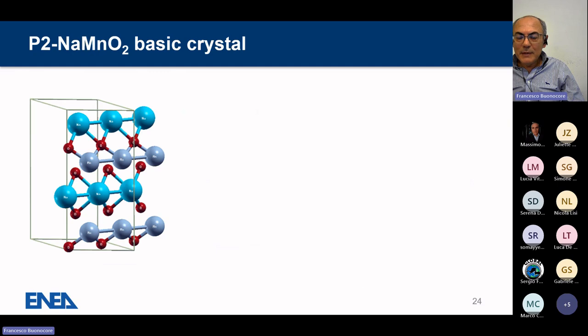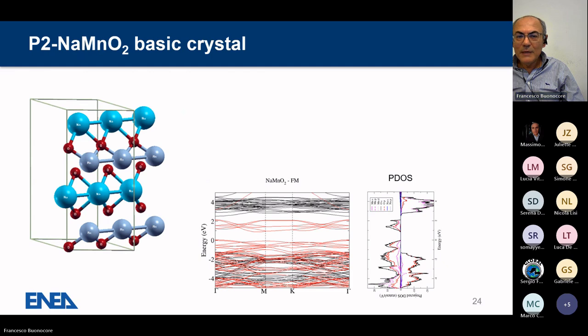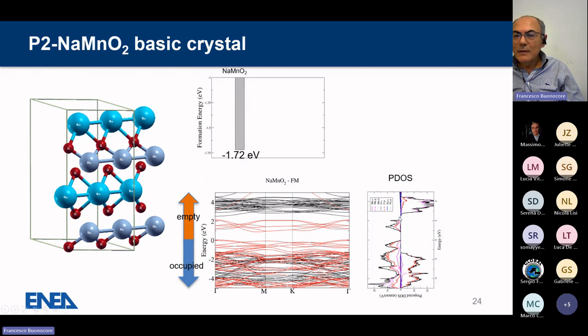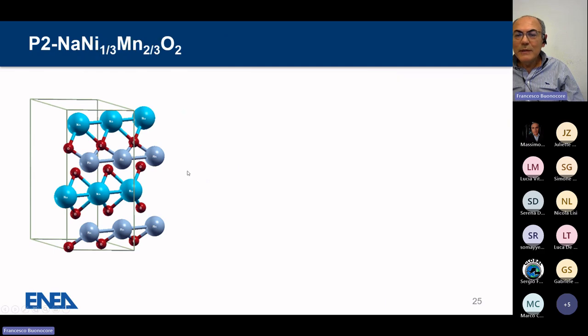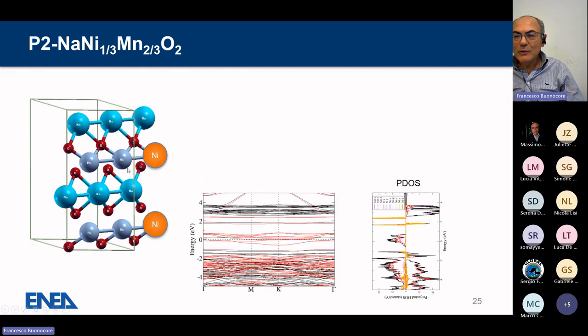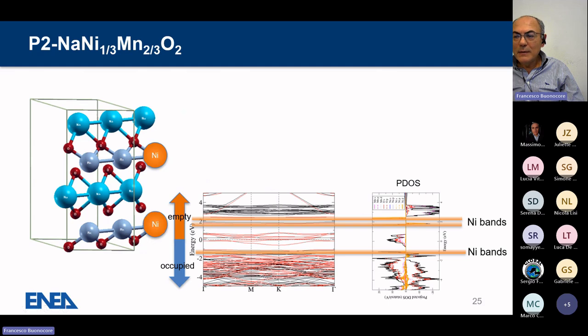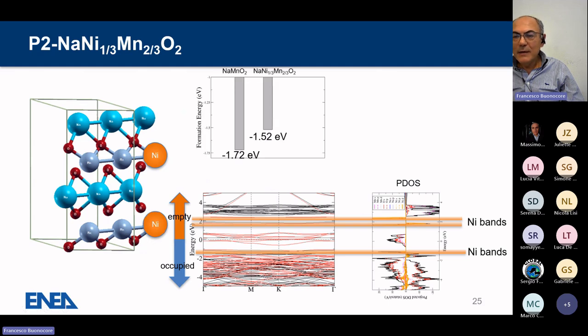And in the next presentation, Marco will tell us more about this. This is some example for some crystal we have selected. This is a crystal with 24 atoms. We calculated the band structure, the density of states, the formation energy and the redox potential when we have the manganese oxide crystal. When we substitute, for example, nickel to manganese in these configurations, we have new bands that result from the nickels, and we have a new formation energy.